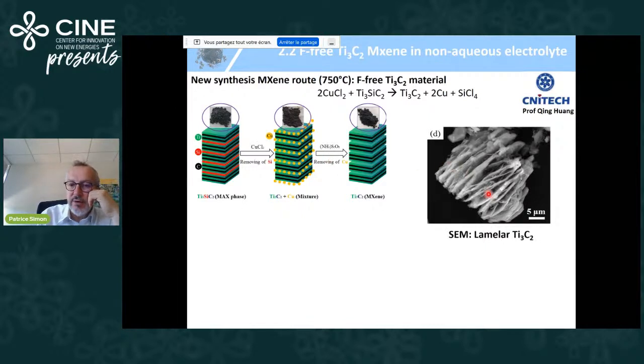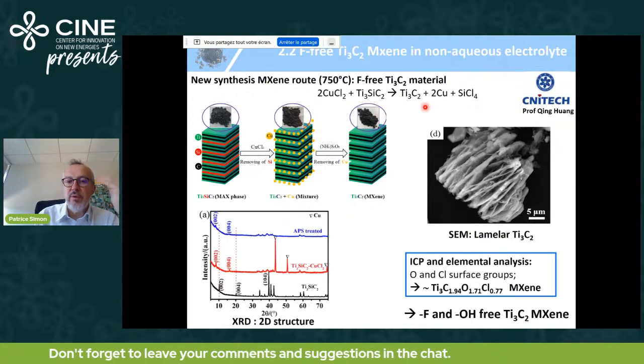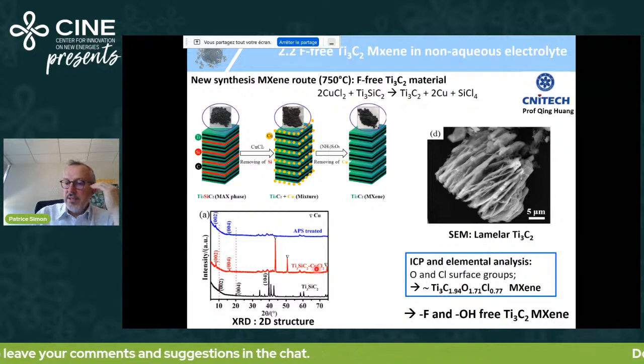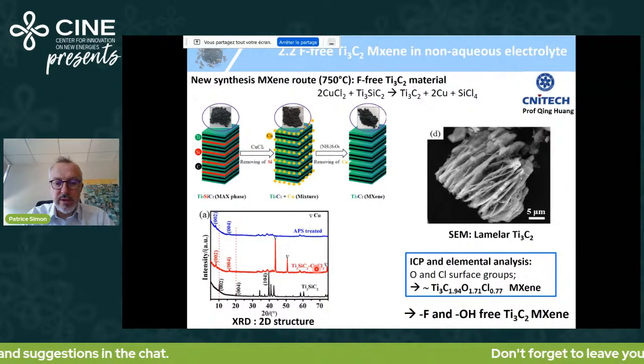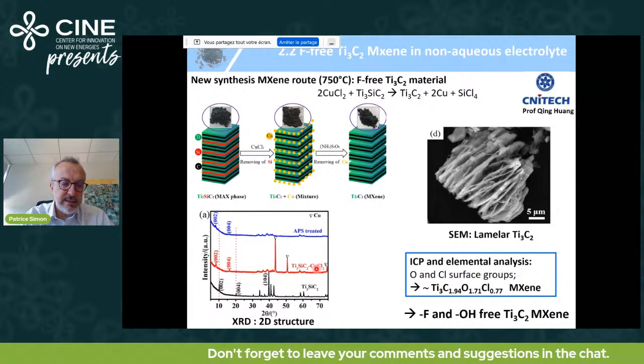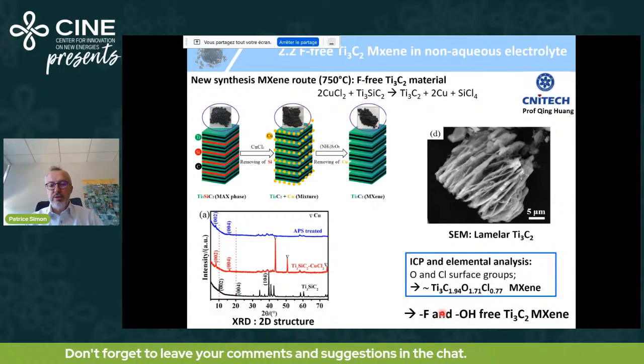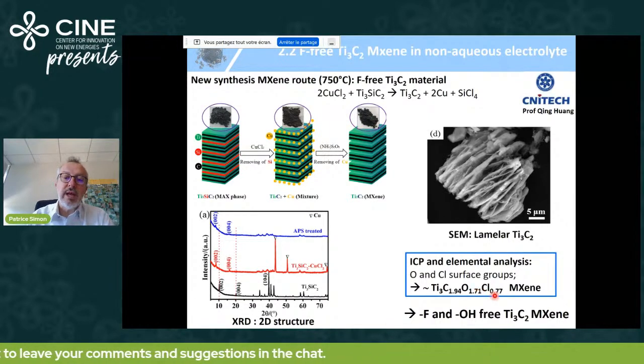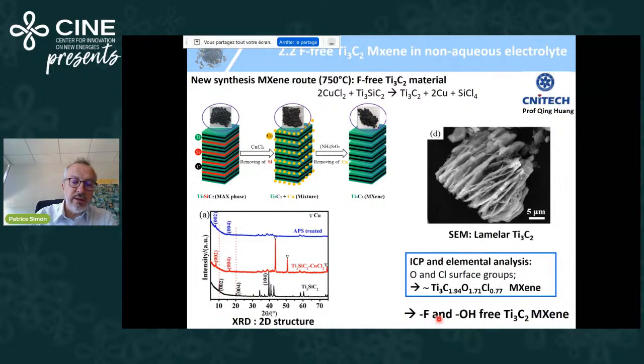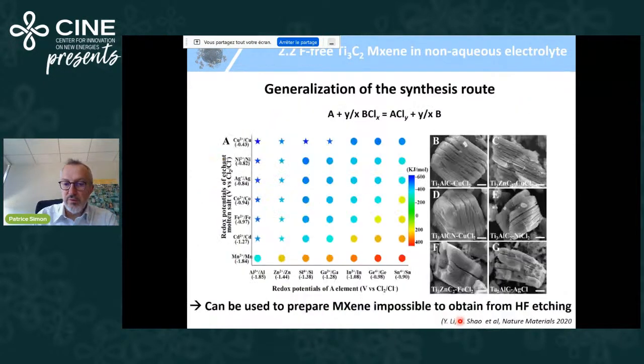And as you can see here, we succeeded in preparing exfoliated MXene materials. And the key point here is that there is no fluorine element in this electrolyte for preparing MXene from MAX. And the XRD is the same. And what you can see from the ICP and elemental analysis is that you end up with a composition of Ti3C2, more or less, with oxygen and chlorine. No fluorine, no OH group onto the MXene surface.